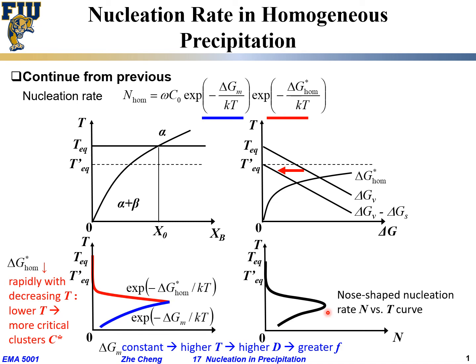This nose-shaped curve is very important for metal processing — not so much for ceramics, but very much for metals. For example, in aluminum alloys, to form precipitates that strengthen aluminum for aerospace applications, you quench from single phase but to an intermediate temperature: not too high (precipitate does not form) and not too low (precipitate also does not form). Somewhere in between, you quench and get precipitate coming out at maximum rate and maximum density. The correct quenching temperature — the proper undercooling — is highly specific to each alloy system, different from aluminum to titanium.